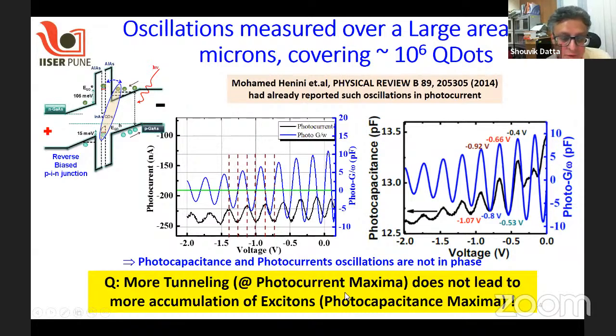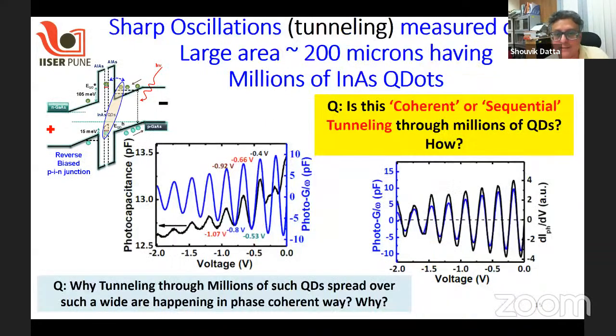However, one thing can be noted: the photocurrent maxima from tunneling do not coincide with the accumulation of excitons, which we may be probing using photocapacitance. So they are not exactly at the same voltage level. We saw these very sharp, well-formed oscillations, which they explain as consecutive tunneling between energy levels of the 2DEG and energy levels of the quantum dot.